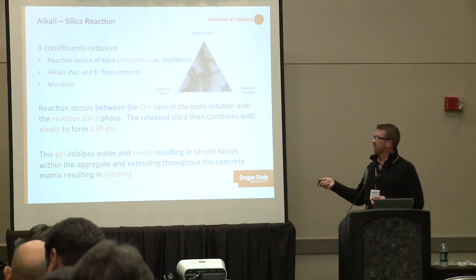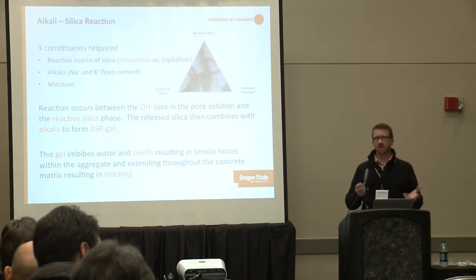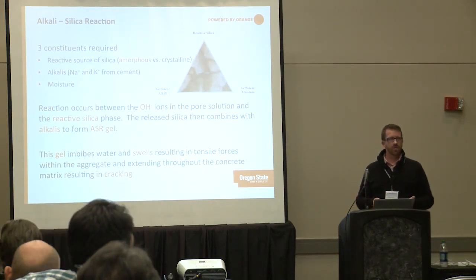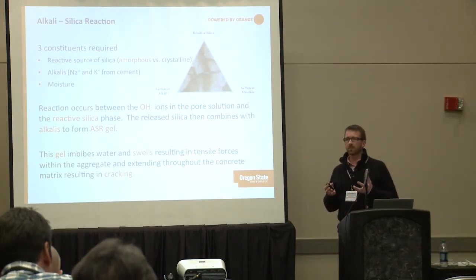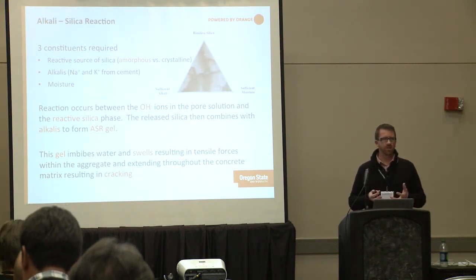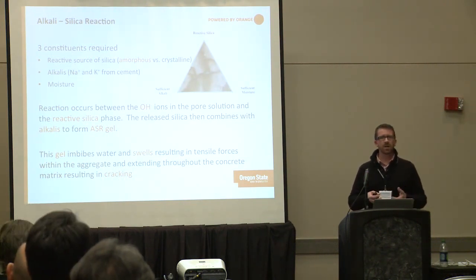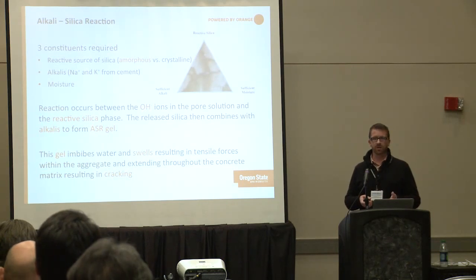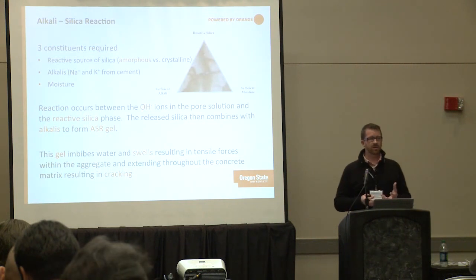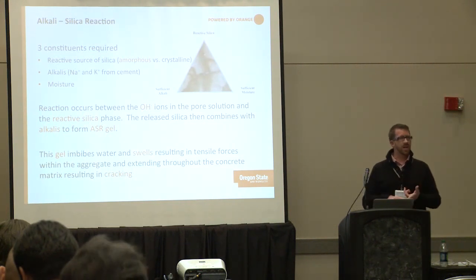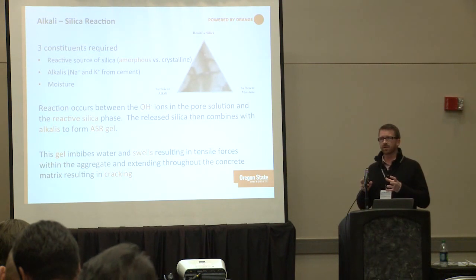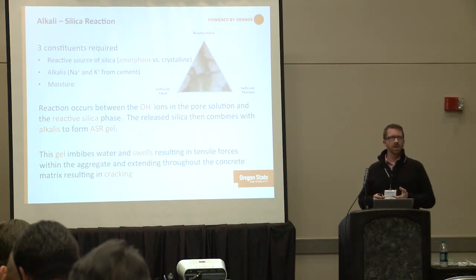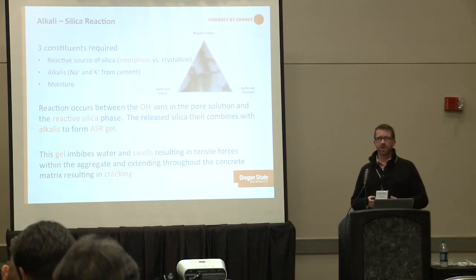This gel then imbibes water — that's where the term alkali-silica gel comes from. Once formed, the gel is hygroscopic, meaning it draws in water. If moisture is present, the gel expands, and if those expansive forces overcome the tensile capacity of the concrete, you will get cracking. This occurs inside the aggregates as well as on the exterior, and the gel can exude into the paste causing more expansion and swelling of the entire matrix.